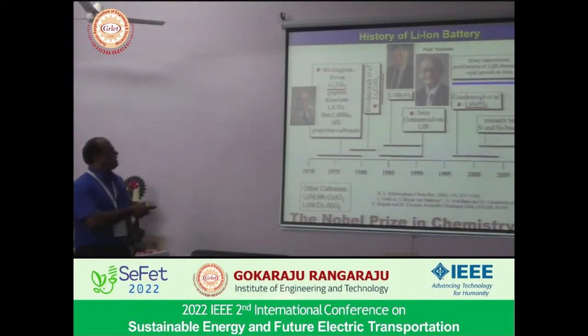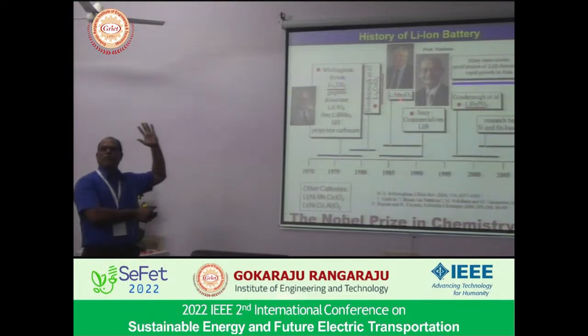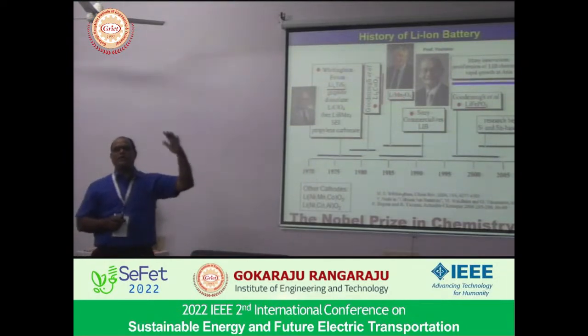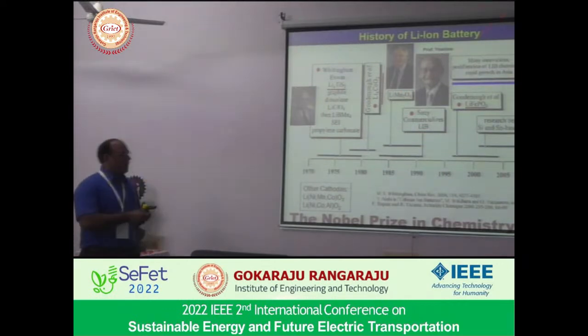In 1976, Professor Whittingham first fabricated a lithium-ion cell using lithium titanium sulfide as the cathode and lithium foil as the anode material. The problem here is the voltage is low, only 2 volt, which is equal to the lead acid battery. Again, the energy density is low. In 1980, Professor Goodenough replaced the lithium titanium sulfide with lithium cobalt oxide, where the voltage can go up to 4 volt. Whenever you increase the voltage, the energy density also becomes higher. So by replacing the lithium titanium sulfide with this material, he increased the energy density, but he still used lithium foil as the anode material.